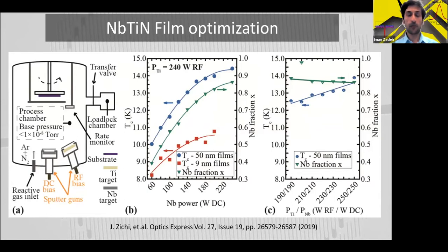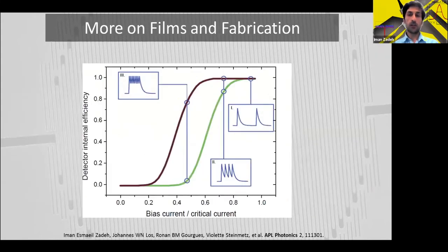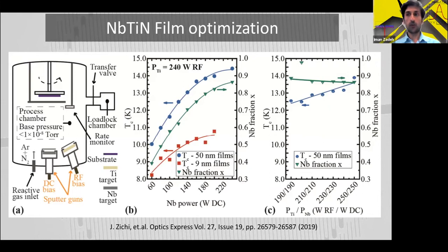So what an experimentalist can do is to sweep the parameters and at least try to find the local optimum. And that's what we did in this paper for telecom wavelengths, 1550 nanometer, but we would also like to do this for other applications. For example, the application in this paper is around 800 to 900 nanometer, which is chosen to match the single photon emitters such as semiconducting quantum dots, III-V quantum dots, and also rubidium and cesium cells for quantum memory.